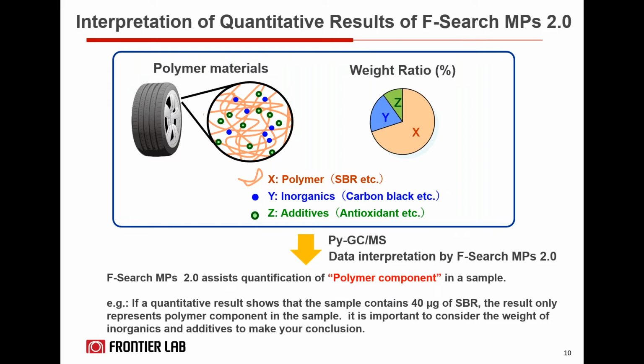So for example, if a quantitative result from F-Search MP shows that the sample contains 40 micrograms of SBR, this result only represents the polymeric component in a sample. So it's important for you to also consider the weight of inorganics and the additives to make your conclusion. Basically, as you know, with Pyrolysis-GC, you're analyzing the organic fraction of your sample. The inorganics remain inside the cup, and the additives can also be identified using F-Search 3.6 libraries. That is a broader MS library engine we offer for evolved gas analysis, thermograms, additives, and polymer analysis as well. But the F-Search that I'm focusing on today, F-Search MP 2.0, is specifically for microplastic analysis.